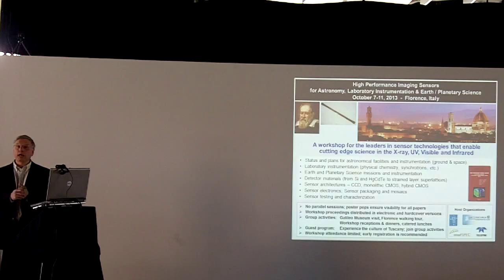People are growing on alternative substrates. First of all, you can try to make those substrates of CdZnTe bigger, and maybe there are some developments that way. Or you could grow on alternative substrates like silicon, which is very inexpensive to get as a big wafer that's very smooth. But the lattice spacing of silicon versus HgCdTe is an 18% difference. It's like putting eggs in an egg carton. If you have the wrong size egg carton and you try to put the eggs in, they don't line up right and they get jumbled up. And then there are some other alternative substrate materials. So we're pursuing that, and other companies are doing that, where you can make them bigger and less expensive so you don't have that expensive substrate. But that's just one part of growing the material.